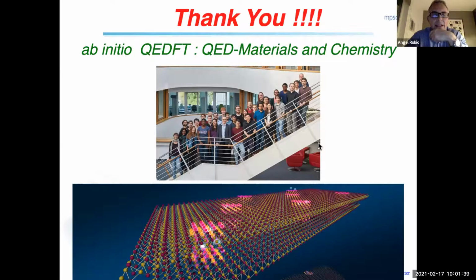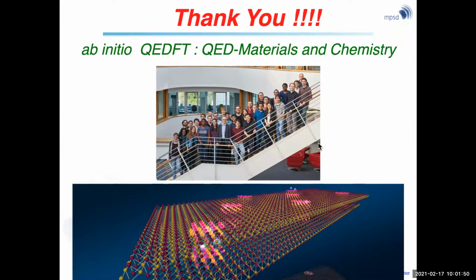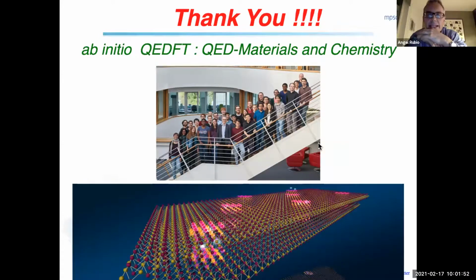No, okay, this is not equal because I was taking two different heterostructures. It was molybdenum disulfide and tungsten disulfide, and they have different energies. In the case that you are talking about, which is a homo bilayer, you will have this hybridization, which will be a linear combination of bonding and anti-bonding excitonic states. And this is what allows you to create this moire lattice of excitons in these homo bilayer systems.